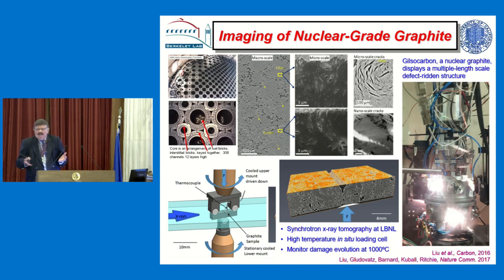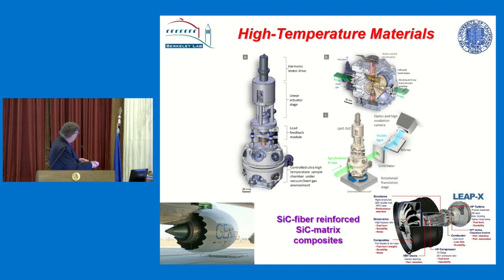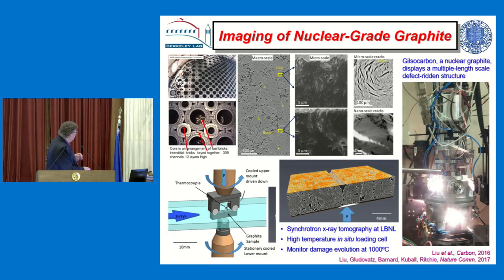So how do you study the mechanisms in this? So we developed a system, which goes in the synchrotron, where we have a little testing machine basically here. This is a loading machine here, and we can measure the stress and strain just like a regular testing machine. But we shine the X-ray beam through the machine, through a window, and we can take tomography images of the material. We can look right through the material, which is very, very interesting. And so this is what it looks like. This is the machine. You can see the light, because we heat the material with what's called heat lamps, so we can go from room temperature to 2,000 degrees in about 10 seconds.